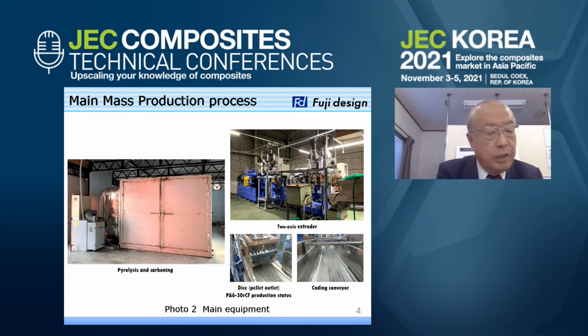After pyrolysis of CFRP or prepreg, we can get RCF that keeps the same properties as the original virgin carbon fiber, and it will be chopped to 10 to 25 millimeter length for good feeding property to a twin screw extruder. On the right hand is a twin screw extruder in Japan. And another application uses RCF fiber of around 100 millimeter length to make non-woven fabric.